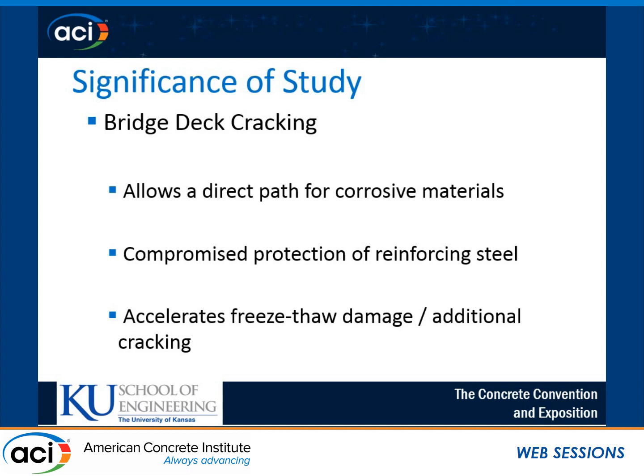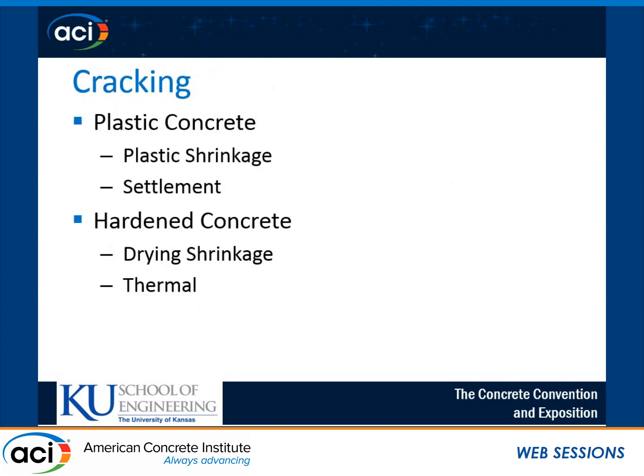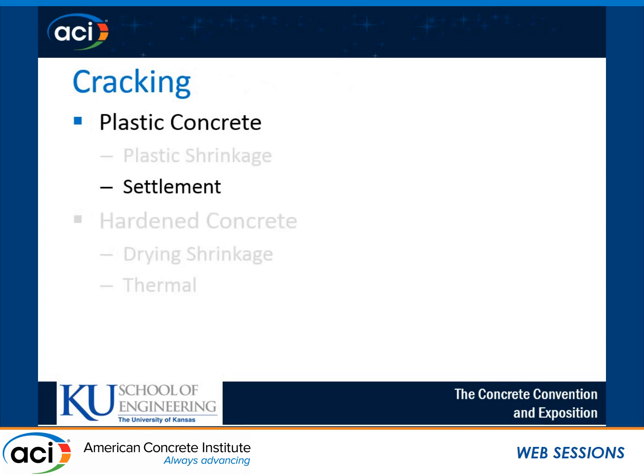And for any water that penetrates down in there for freeze-thaw prone regions, you can have damage due to that too. So the main culprits of cracking that we deal with in our research are both in the plastic and hardened state of concrete. So we have plastic shrinkage and settlement in our plastic state, and after the concrete hardens, we deal with drying and thermal mechanisms there. But for this presentation, we're focusing primarily on settlement cracking.